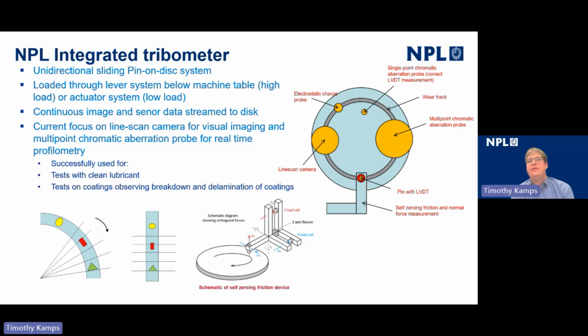we programmatically account for the refractive index of both the 3D probe, which is a multi-point chromatic aberration line scan probe, and the line scan camera, which is a light intensity camera. And we can focus this through the lubricant film and image the wear track underneath the lubricant film. So if we're looking at the formation of an oxide film, for example, we can measure that. And this multi-point chromatic aberration probe has a resolution that allows us to see very thin films. We can also look at tests on coatings, observing breakdown and delamination of coatings.